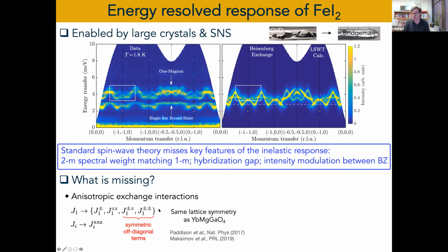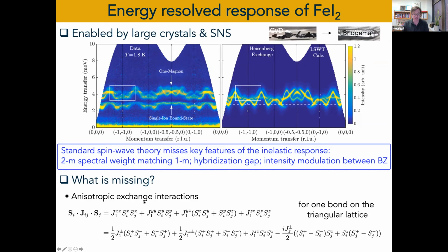So I don't want to go too much into details. There are several ways to parameterize this. We call it J1 plus minus, Z, and plus minus plus minus. It's just a certain parameterization of the off-diagonal exchange interactions. In fact, you could represent the same Hamiltonian with simply a J plus-minus, Jz, interaction. And when you go from one bond of the lattice to the next bond of the lattice, you have to apply a rotation matrix, et cetera.